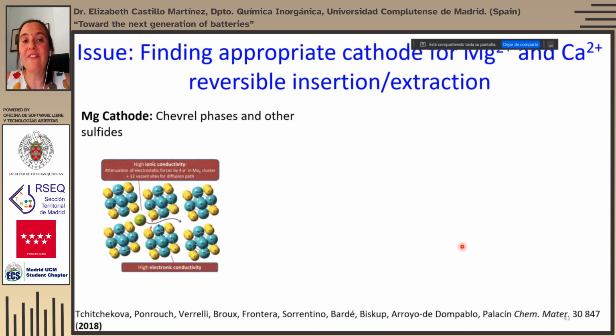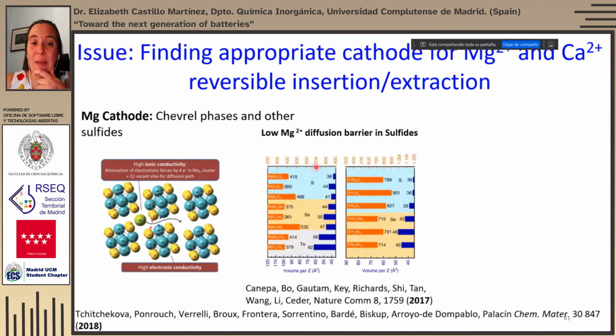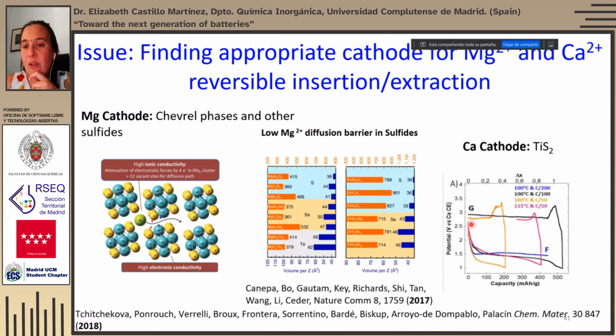Another issue with these multivalent chemistries is that it's difficult for the cation also to be inserted and extracted from a cathode host. Indeed, softer anions, such as sulfides, are preferred for the cathode material rather than oxides. And for magnesium batteries, it's the Chevrel phase, the molybdenum sulfide phase, which has shown the best performance, although the magnesium diffusion barriers are not very large in some sulfides and selenides as well. But for calcium, the best performance achieved so far is with titanium disulfide, and this takes place at very high temperatures and still relatively low C rates. So there is a lot of progress still to be made for these technologies to actually reach the market.